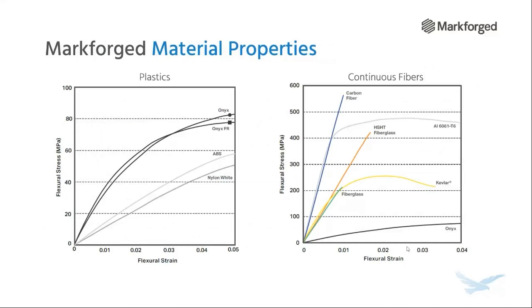And starting out with the plastics there on the left-hand side, we have Onyx, which again, it's a very strong printed material, mainly due to the inclusion of that chopped carbon fiber. And it's stronger than another common printing material that you're going to see out there called ABS. But again, that real strength comes from reinforcing an Onyx part with the continuous fiber. And you see Onyx on the right-hand side of the screen. It's at the bottom of this chart when we're looking at parts reinforced with fibers. And the carbon fiber actually outperforms 6061 aluminum in a flexural test. And notice the behavior is very similar in the linear region of the curve here, yet carbon fiber is able to reach those higher flexural stress values before breakage.